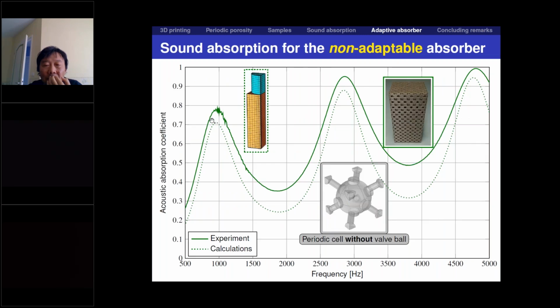And finally, the final results. This is the experimental results for the sample without valve balls. You see that the predictions are very similar to the measurements. There's underestimation of the absorption, because in the calculation, everything is idealized, very smooth.